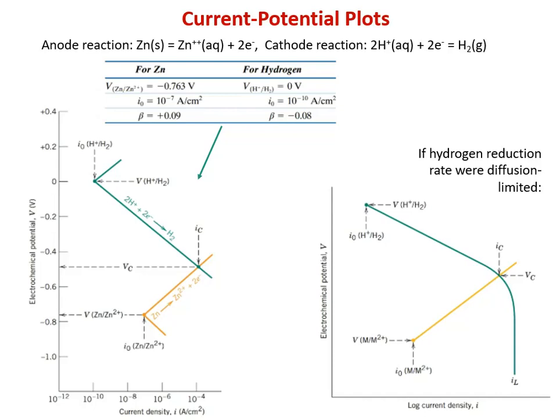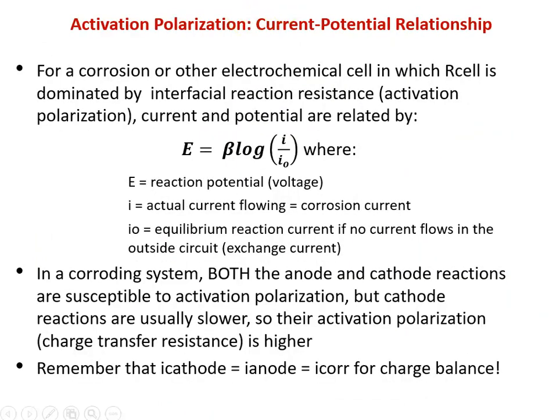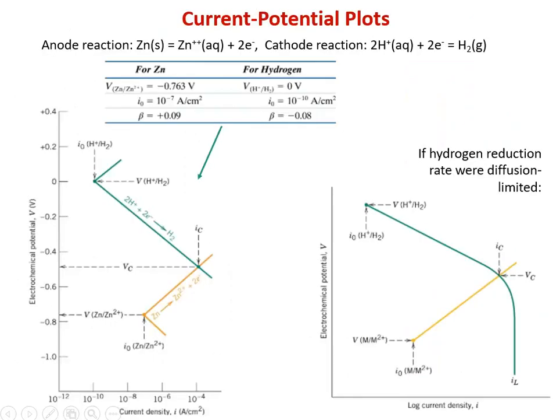So we started at 0, our standard conditions for our standard hydrogen electrode, oddly enough, because we are talking about reduction of hydrogen. And as we demand that that happen at a higher and higher rate, we increase our current for that reaction effectively, we see that the electrochemical potential drops. Well, that's happening with the log scale, so that's where we're seeing that logarithmic dependence here, this E versus log I over I0. And it would go in the other direction if we forced it to run in reverse.